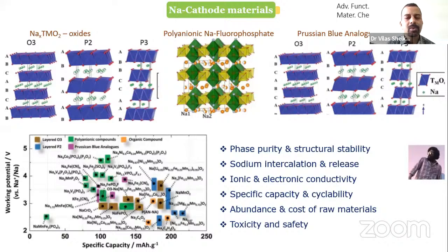And similarly, for sodium and all these materials used in the fabrication of the cathode, there you can see the compositional variation. There is manganese, cobalt, nickel as well. They may give you a better performance, but for commercial purposes, you should know how to exclude these materials which are not domestically available or which are costly. Again, there are some elements like vanadium or chromium, they can give you better performance, but there are issues with toxicity and safety of these elements. So again, you have to make a compromise sometimes on the specific capacity or cyclability to avoid toxic or unsafe elements inside your battery.